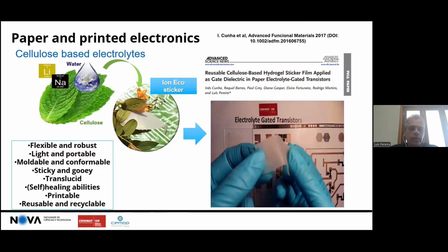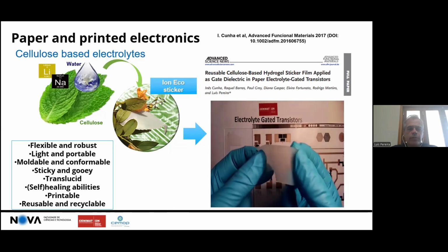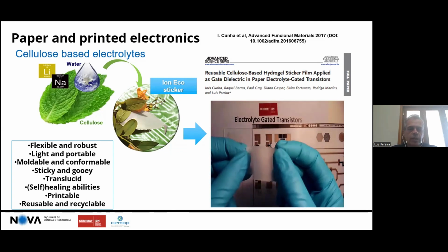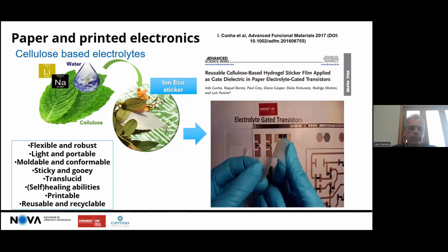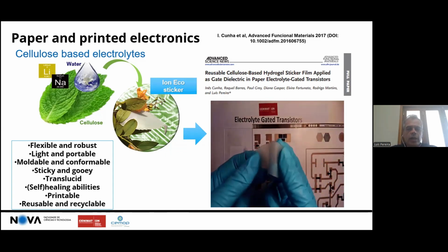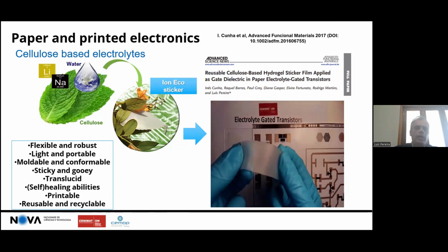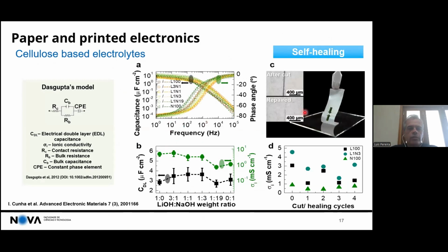But we can also do another thing, that is, instead of using the paper itself as a dielectric, you can develop specific electrolytes, also made of cellulose, that can be used on transistors and replace the paper as a dielectric. So we also developed this, made from cellulose derivatives. And the idea was that, also, this is just a curiosity, of course, they can also be self-healing. They present self-healing properties. So if you damage them, they can recover the mechanical properties and keep, more or less, the ionic conductivity always close to or above 1 millisiemens per centimeter. That is perfectly enough for this application.